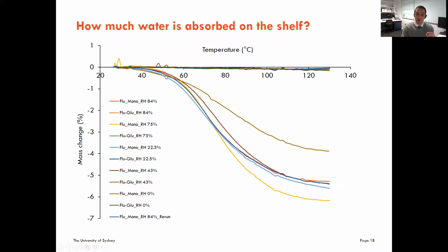What we did here was called TGA, a thermogravimetric analysis. We stored both our co-crystal powder and the monohydrate powder in different relative humidity chambers, ranging from 84% down to 0%, stored it for a week, and then we put it in the machine that will heat it up from about 25 degrees up to about 130 degrees. It measures the mass change as it heats up. Obviously, as it heats up, water is going to evaporate off, so the mass is going to get lower, okay? The greater the amount of water that has been absorbed in that week of storage, the greater the mass change you're going to have.